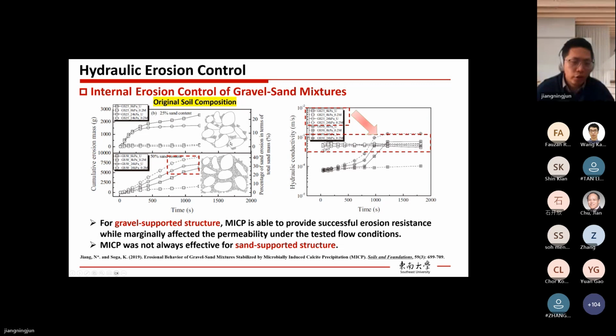So for these two structures, after we did the erosion test, we find that MICP works very well for the gravel supported structures. It can effectively cement the sand particles so that they will not migrate through the pores. But for the sand supported structures, MICP is not always effective. In some cases, it could be worse, especially if we have a high level of vertical stress. This is because we simply have too many sand particles. And if the cementation is not enough and we have high vertical stress, then stress can push the uncemented sand out of the soil structure. So we see a lot of erosion mass. And if we look at permeability in this case, the permeability also increases dramatically because of the loss of sand particles. So this result demonstrates the importance of original soil composition.